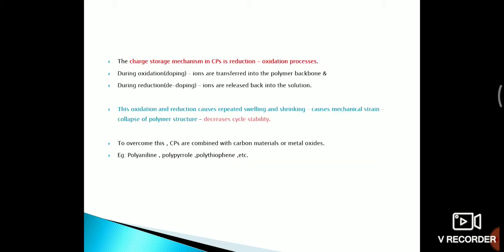The charge storage mechanism in conducting polymers is the reduction oxidation process. During oxidation, the ions are transferred into the polymer backbone and during the reduction they are released back into the solution. This oxidation and reduction causes a repeated swelling and shrinking of the material, which causes mechanical strain in the polymer and leads to the collapse of the polymer structure, and it decreases the cycle stability of conducting polymer based supercapacitors. To overcome this problem, the conducting polymers are combined with carbon materials or metal oxides to increase their cycle stability. Examples of conducting polymers are polyaniline, polypyrrole, polythiophene, and its derivatives.